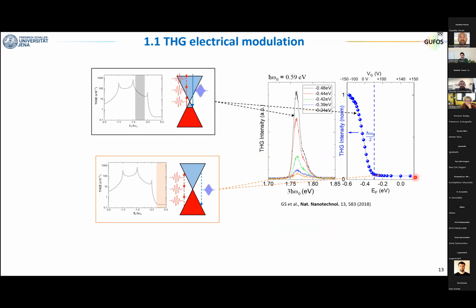And you see that when we are close to 0 Fermi energy, this is what we call the non-resonant case, the third harmonic is very weak, close to 0. And then there is this special point at the dotted line where the Fermi energy is half of the photon energy. And from here, we have this very strong increase in the third harmonic generation efficiency.